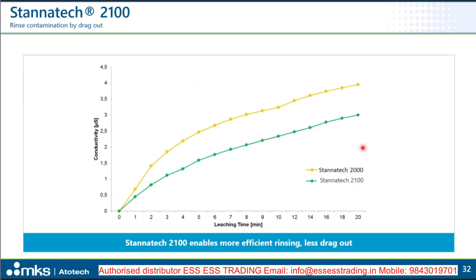And what you see in this graph here is the conductivity measured in the rinse after the immersion tin process, after certain times when the panel from the tin process was immersed in the rinse. And what we see is that for the Stannatech 2000, which acts here as a reference, a higher conductivity can be observed compared to the 2100, meaning we drag more of the plating chemistry into the rinse, meaning also that we need more rinse water and more activity in the rinse to get rid of the chemistry compared to the 2100. So the 2100 is, due to the lower viscosity, easier to rinse off and brings less drag out into the rinse, so it also helps to reduce rinse water consumption.